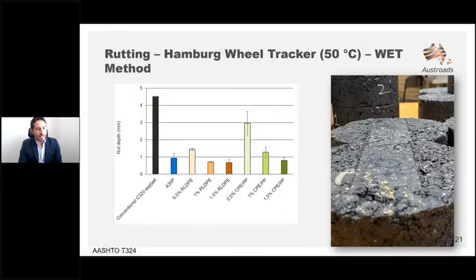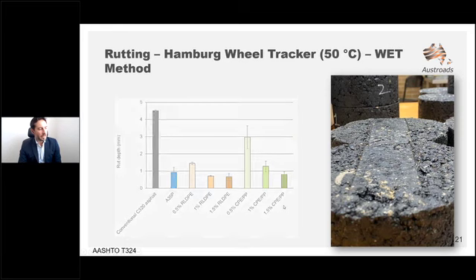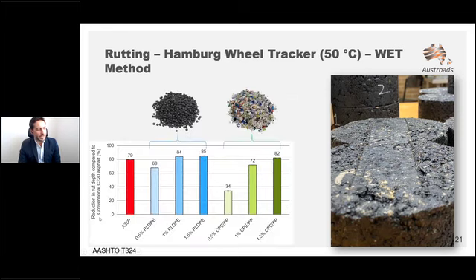In terms of rutting, the mix method is probably very good and probably much better than the other two methods we've been discussing in the past webinars. This is the rut depth of standard asphalt, and these are the other mixes that we've tested. Now, just to give you a bit of a better overview and provide some more details, I've plotted here the reduction in rut depth compared to the standard unmodified asphalt.